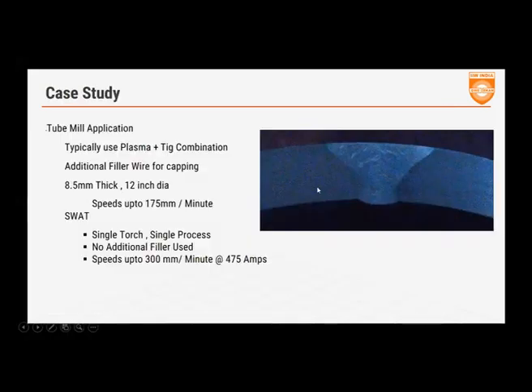If you can see the case study on tube mill applications, typically tube mills use a plasma plus TIG combination. So they have TPT or TP as a combination. The plasma makes the keyhole, the TIG fills it up. You have a filler wire addition required to meet the capping needs. 8.5 mm thick, 12-inch diameter pipes are being formed at about 175 millimeters a minute on the tube mill with a plasma plus TIG combination.